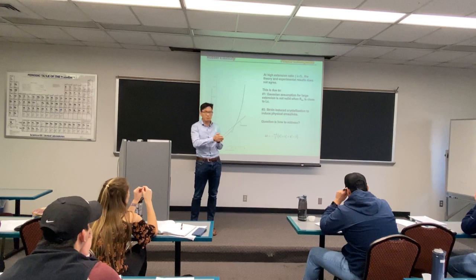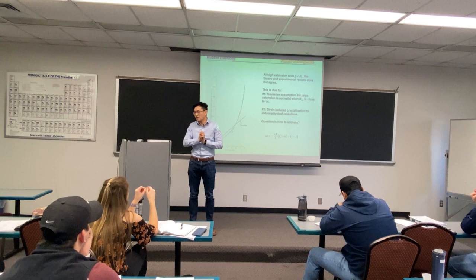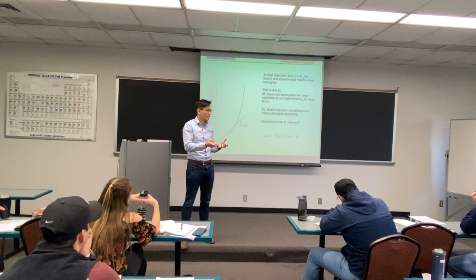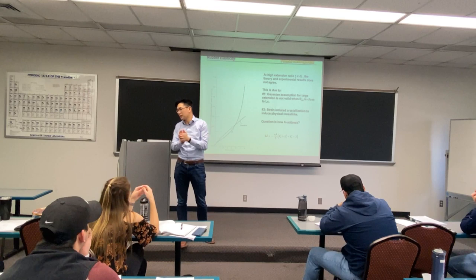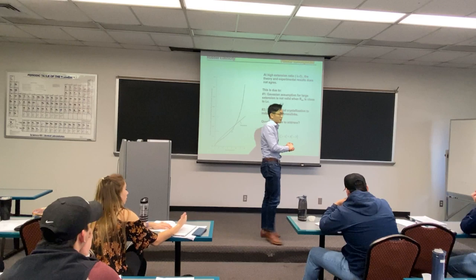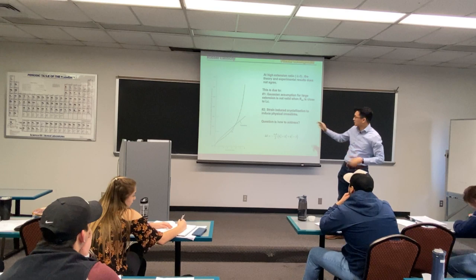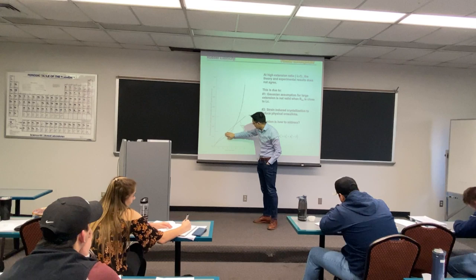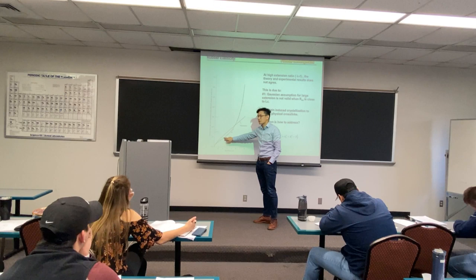And once they start to crystallize, they act as a physical crosslink, not a chemical crosslink, but physical. In the crystalline region, you have chains bonded together very tightly. And effectively, although you didn't directly increase crosslink density, it's physically increased when crystallization happens. It typically happens here. And once this physical crosslink forms during crystallization, the stress starts to go up very rapidly,